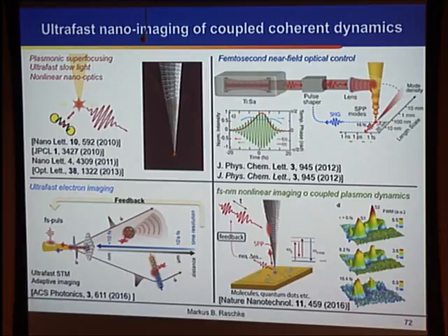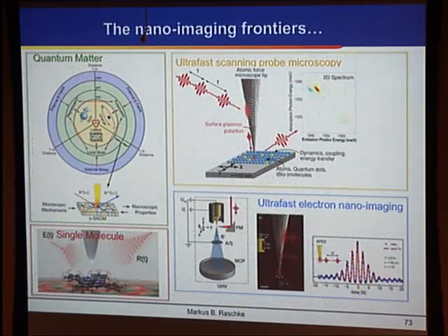So this is why a lot of the techniques I mentioned in the beginning, whether you do X-ray, electron, or optical nanoprobe, do connect and allow for new imaging modalities by combining these different capacities. Where we are pushing the technique now is to do single molecule ultrafast spectroscopy. We are currently already at the single molecule limit. We can probe single proteins in IR spectroscopy. This means that we are sensitive to about 400 vibrational oscillators. This is an increase of about 10^6 compared to far-field IR spectroscopy.